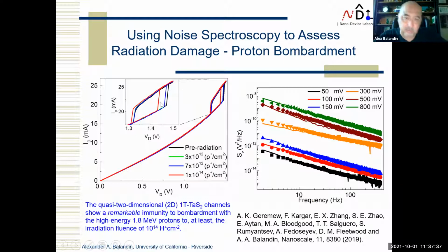So you can see again this working window under strong proton bombardment and large dose. The IV did not change, so it means that it would oscillate the same way. And now we used our low frequency noise spectroscopy also to show that sometimes damage from radiation cannot be seen easily in IVs, but it would be seen in low frequency fluctuations. And so you can see that there is very little change. This is the noise level before and after.